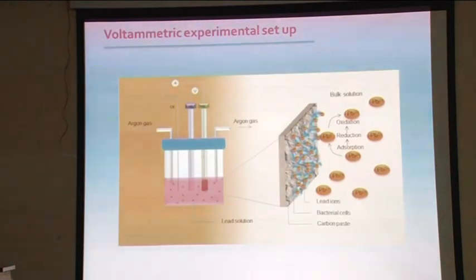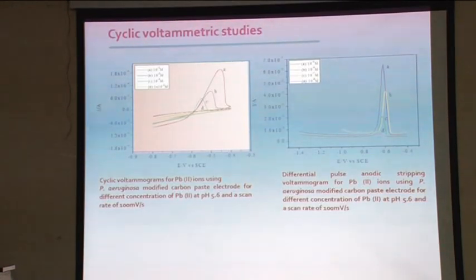So, as I talked about, we did a novel electrode. A carbon-based electrode was modified using these microorganisms. So, we have a typical three-electrode assembly here. And we are able to use this as a technique for remediation. You can see the cyclic voltammetric tests that have been done. You can see that of the order of 10 power minus 5, you will be able to detect.